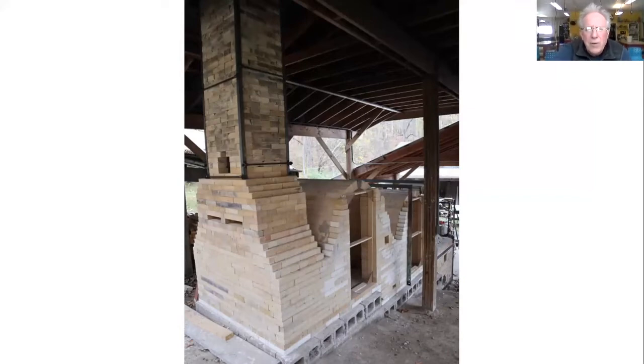The hole up above in the chimney that you see there is a passive damper. If you pull the bricks out of that during a firing, it slows the draft of the chimney down. And so that's one way of slowing the speed of climb in a kiln. It's also a way of introducing a little more reduction or more buildup of gases in the chamber, which bring the color to the clay.